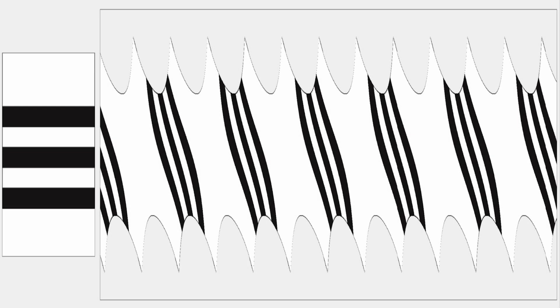You can see that the original core of the blade has 3 bars and that each bar is a laminate of 7 layers. 2 thick white layers on top and bottom, while at the center there are 5 thinner layers alternating black and white. 3 of those are black and 2 are white. The total thickness of the central 5 layers closely approaches the thickness of each of the top and bottom white layers. With this information, we can now go back to recreate the pattern in Thor.